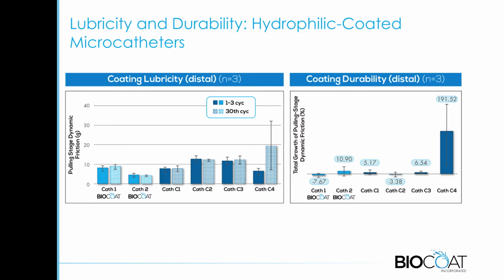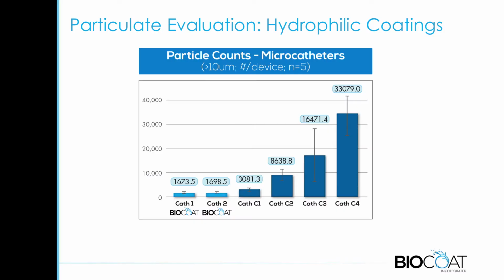There was one of the catheters where the durability was not quite as good, as you can see that changed. But most of them were pretty good in terms of the durability as well as the lubricity. And if you think about it, this is how most people evaluated coatings up to 7 to 10 years ago. You had the lubricity and the durability. But when you look at the particulate piece, it kind of changes the interpretation of these coatings.